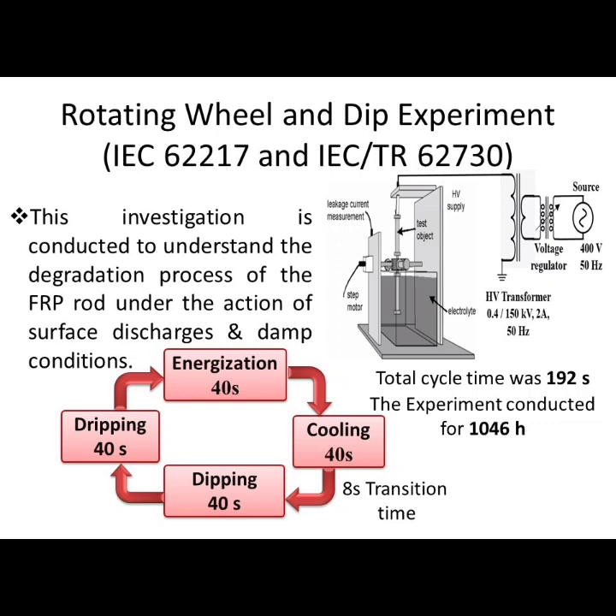The period of each stage is 40 seconds with 8 seconds transition time. So the total cycle time will be 192 seconds. This experiment is conducted on the bare FRP rod samples for 1046 hours to evaluate their performance under the worst case scenario, where the FRP rod will be exposed to conducting water film and electrical discharges. The circuit diagram of this experiment is shown here.